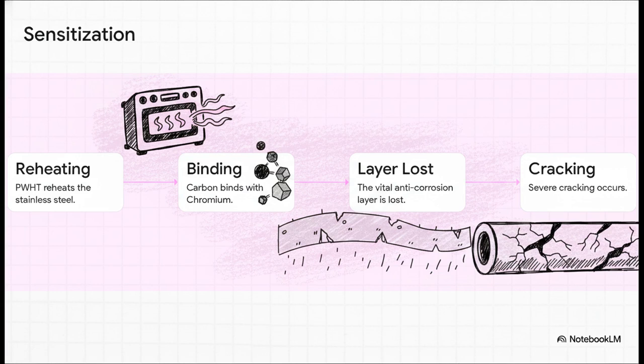First, the heat treatment slowly warms up the stainless steel. As it's just sitting there baking in the oven, these tiny trace amounts of carbon inside the metal wake up. They get highly active and actually start binding with the chromium. Because the carbon is suddenly hoarding all the chromium, the metal loses its vital, invisible anti-corrosion shield on the surface. So when that vessel is finally put into service, severe, rapid cracking happens almost immediately.